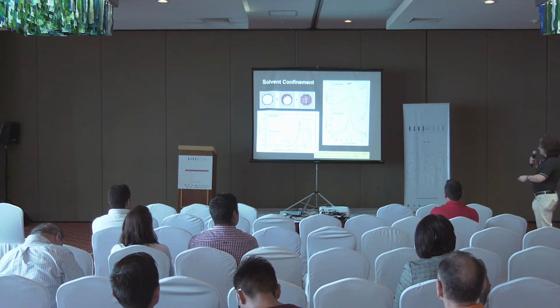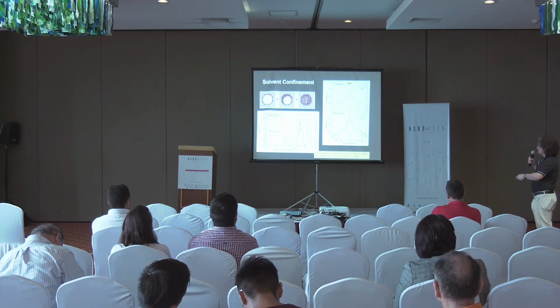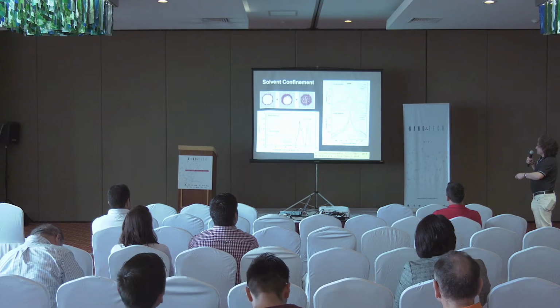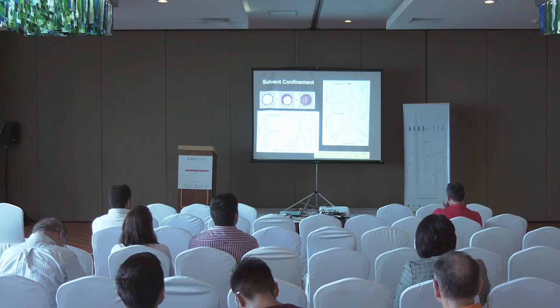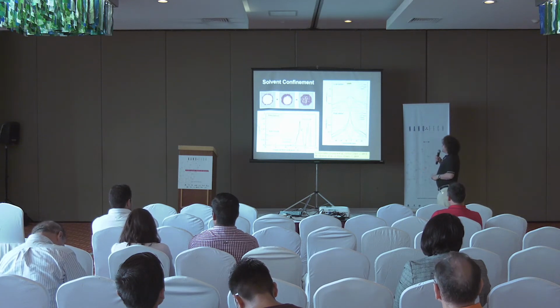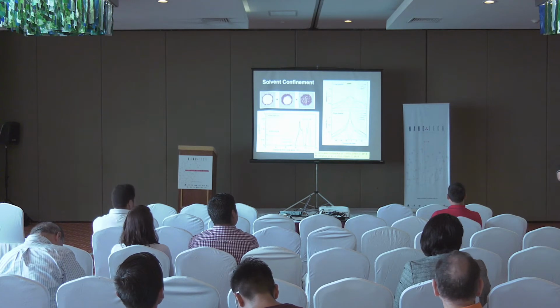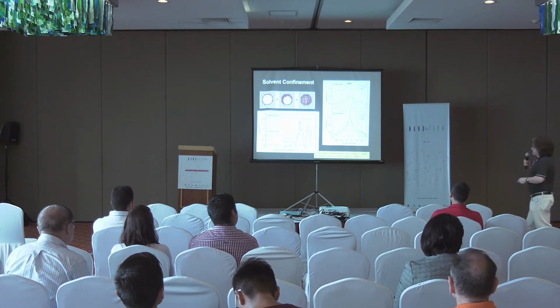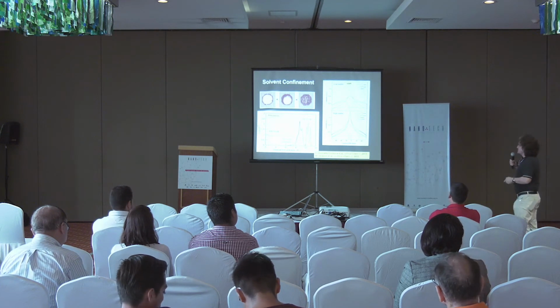You have liquid water in the center of the pore, and you retrieve a density of 1 here, but then you retrieve also the structuring of the water on the walls, and then you have some structuring here. This is the density of water. See these fluctuations. This means that you have some structuration of the water. So the water is not continuously liquid inside a vessel. We measured this also by relaxation NMR. So we could observe that there is a very peculiar and size-dependent story of water here that, for example, has implications in catalysis, in flux, nanofluidics, etc.